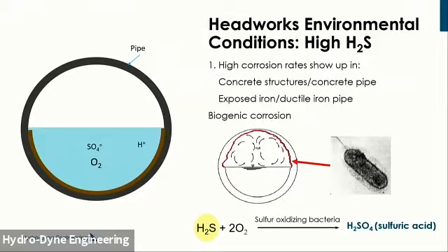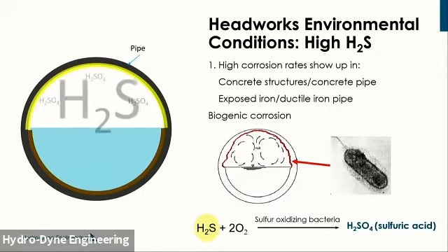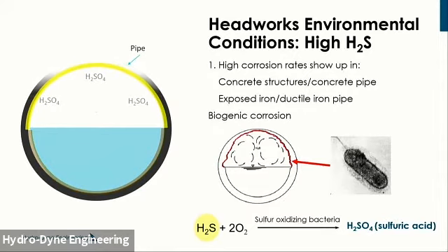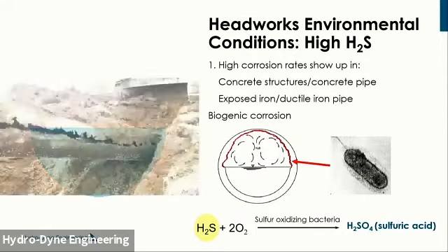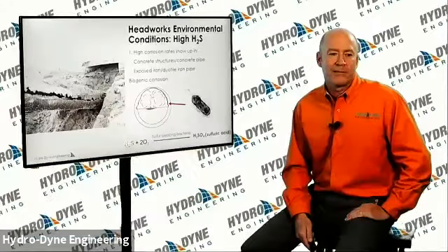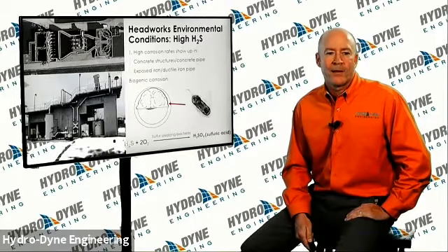Biogenic corrosion is driven by sulfur oxidizing bacteria. They take the H2S, hydrogen sulfide, as it occurs in the system, react it with air, and they can make sulfuric acid. Now we'll play the graphic. So oxygen is depleted. The sulfate is then converted to sulfide. That then can convert to hydrogen sulfide. And then as a gas, that can come out of solution in the system with turbulence. And when it does that, the bacteria then can convert that to sulfuric acid. And the sulfuric acid is the real problem. That can then attack iron and concrete piping. And that's how we end up with a pipe that looks like that. And that all ends up at our Headworks.